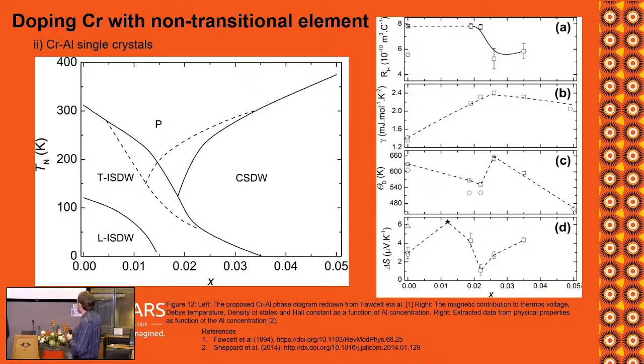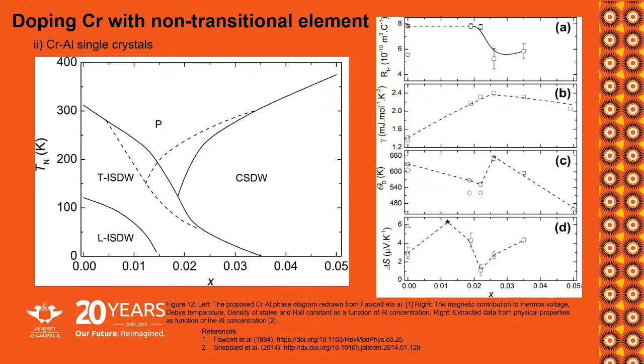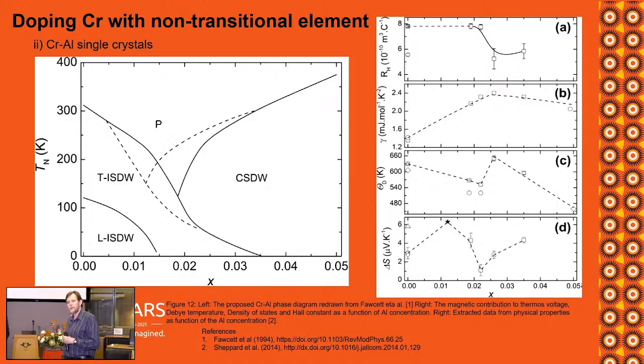Then I worked with Prof. Alberts and worked with single crystals in this case. And on the left here, this gives TN, that antiferromagnetic (Néel) transition, in essence, for the material, as a function of composition. But there's a problem. In published work, that triple point sits in 2 different places. They argue about this. With, of course, these are just an incommensurate spin density wave.